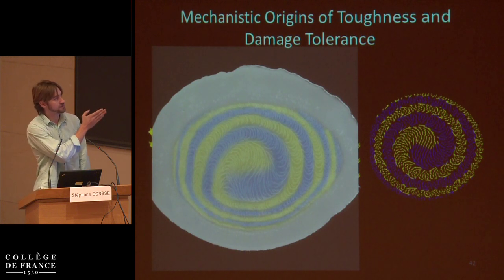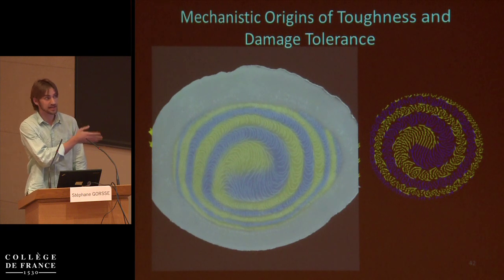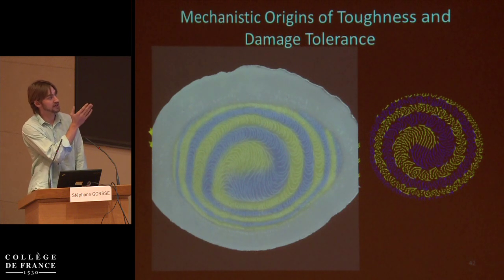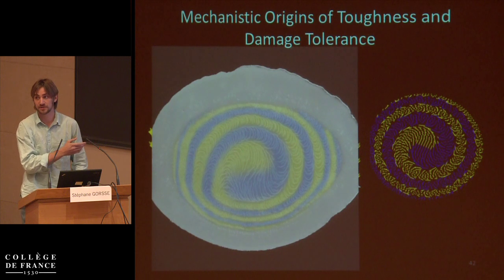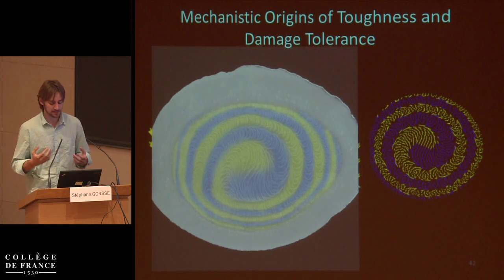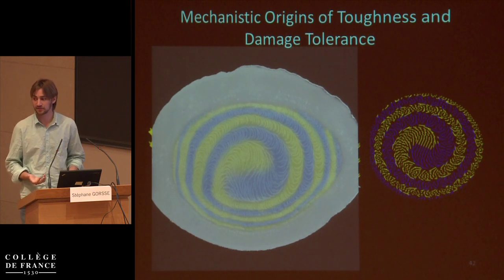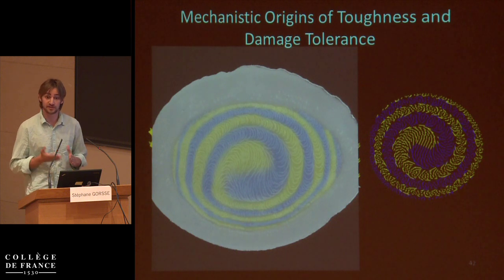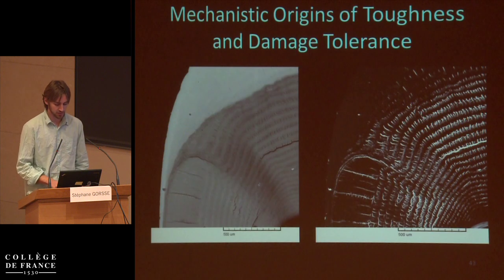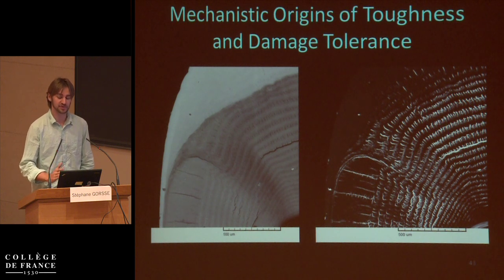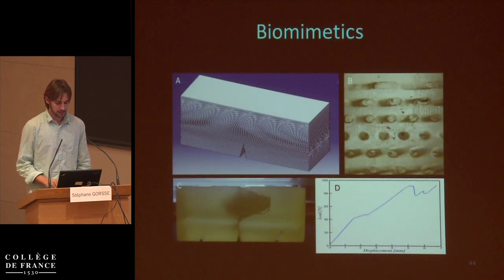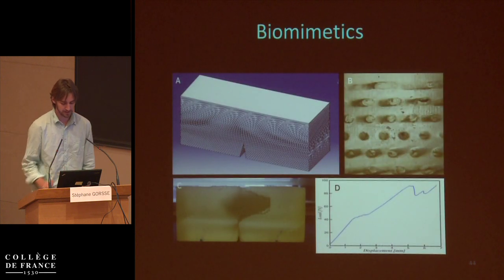the pattern of the fractures, which we're seeing from the charge contrast image, is exactly reproduced by doing nothing but simulating the fibers. So what that tells me is that the fibers are controlling the fractures. So the fractures are always traveling between fibers. So when I look back at this picture, what I think is going on is not actually that fractures are being arrested, but rotating out of the plane of the polished surface. And so to confirm that,